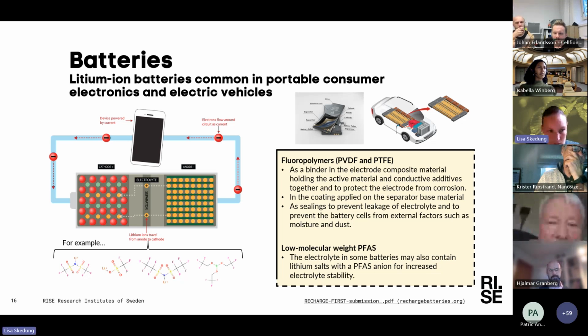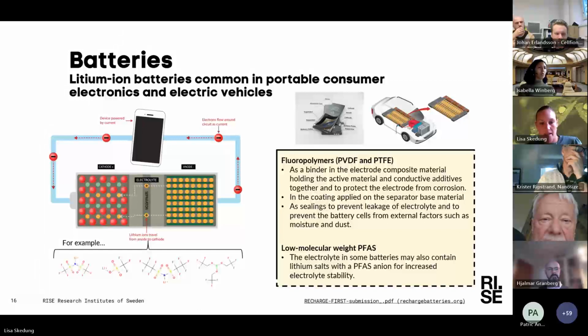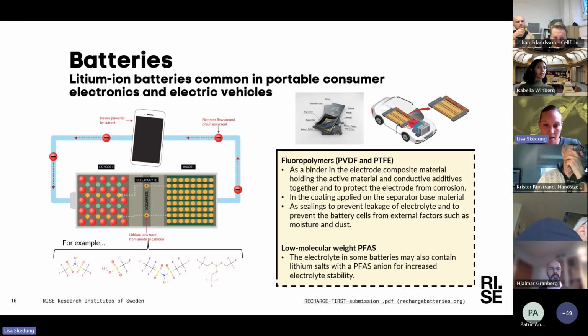And when it comes to batteries, fluoropolymers such as PVDF and PTFE are used as a binder on the electrodes, as well as in the coating on the separator. And another use not shown here is sealants in the battery to prevent leakage of the electrolyte, but also from the outside in.